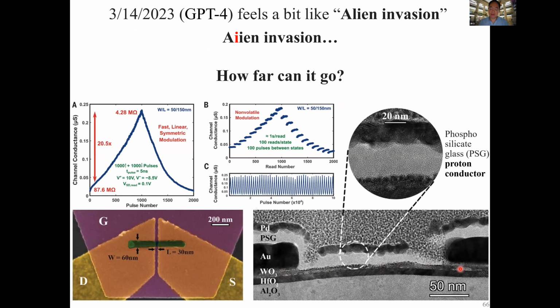And unlike typical semiconductors, where your dopant is fixed, here we are pumping protons across this phosphosilicate proton conductor in real time. So we're dynamically doping the tungsten trioxide and changing the tungsten from valence 6 to valence 5 and changing the electrical conductivity. So this is similar to the ionic channels in neurons. In neurons, we use sodium, potassium, calcium. So we have these ion channels, which change the neurons and synapses, and that will give us the biological brain.